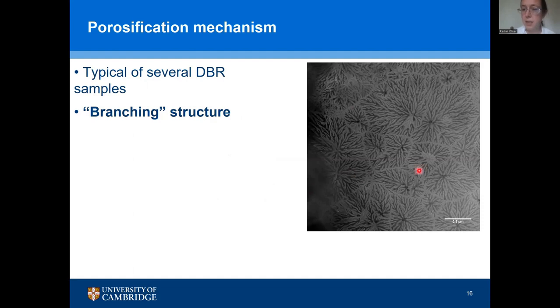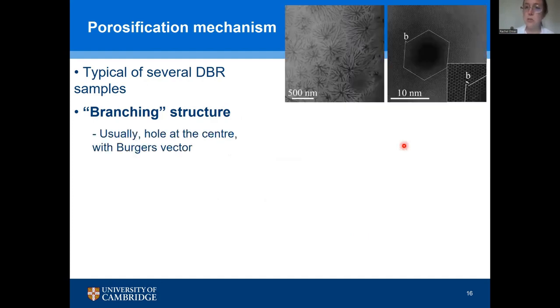So here's another example of the sorts of structures we see, but again, the same pattern. Sometimes we see very branched structures, but again, always emanating out from this central dark dot or hole. What we need to do now is zoom in on that hole. Now, you'll hopefully remember that right at the beginning, I stressed that we have defects, mistakes in the crystal, that run through all these nitride films that are grown on unlike substrates. Here we're growing on sapphire. Those defects are what we call dislocations. They're a line defect, a line of improper bonding in the crystal. And if we zoom in on one of these little dark dots, there is a hole in our sample, we can identify that there was a dislocation at the location of that hole.